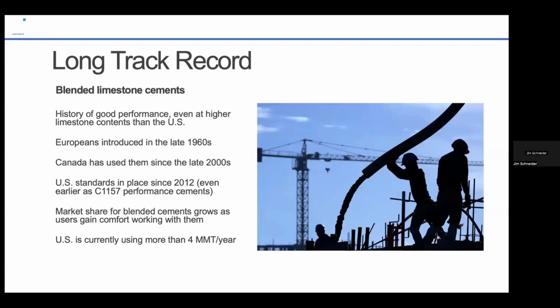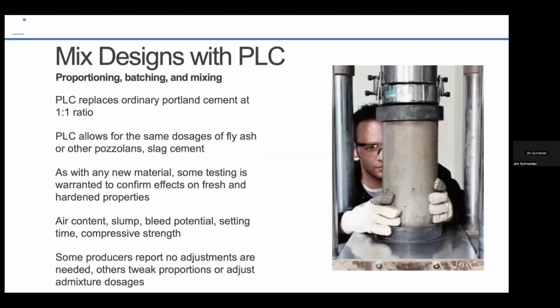Long track record, history of good performance, even at higher limestone contents than the U.S. Europeans introduced this in the late 1960s, as usual. They're ahead of us. Canada's been using them since the 2000s. So this is something that's fairly well established, and we're really kind of starting to catch up to it here and see more of it. So PLC allows for the same dosages also of fly ash and other pozzolans and slag cement, materials that we can use in replacement of cement to a percentage. I'll talk more about that in a bit. As with any new material, some testing is warranted to confirm effects on fresh and hardened properties. Air content, slump, bleed potential, setting time, compressive strength. These are all things that you want to work with your precaster on to make sure that you are hitting the right marks and all that.